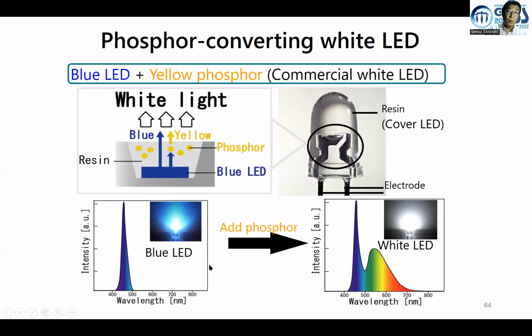This is an example of a combination of blue LED and yellow phosphor, which is actually YAG:cerium. This yellow phosphor, because of the reasons explained below, has a very broad emission spectrum covering the wide visible range, different from europium 3+ and terbium 3+, which are utilized in fluorescent tubes. This phosphor has very broad luminescence. And the good thing is there is no infrared emission, unlike an incandescent lamp, or violet UV region, unlike a fluorescent tube. So the spectrum exists only in the visible wavelength region. That is a good point.